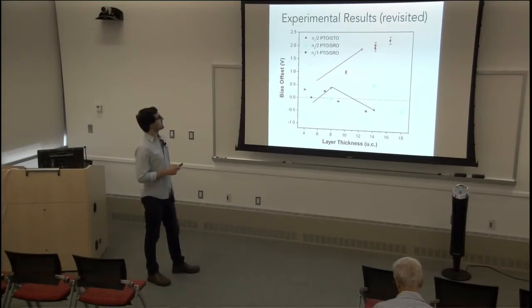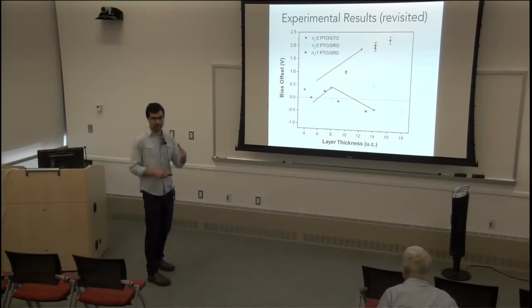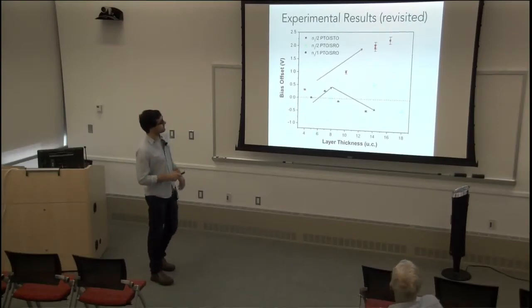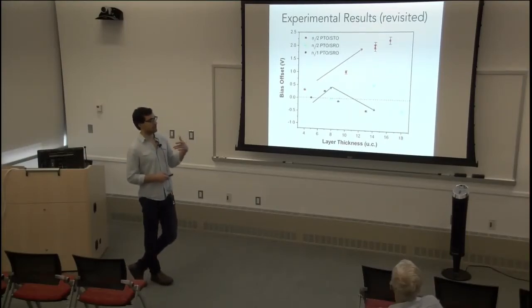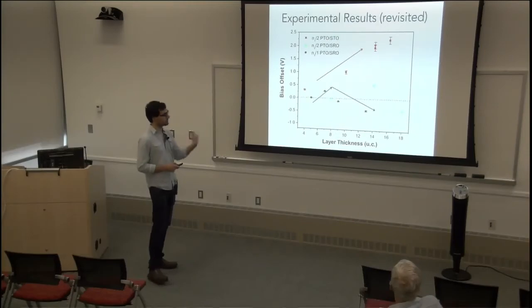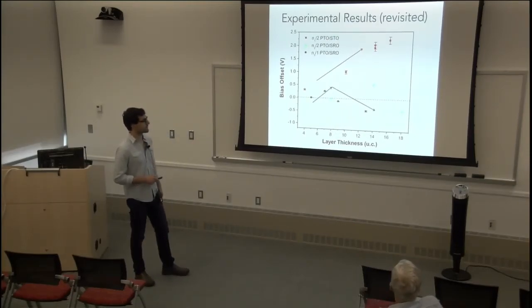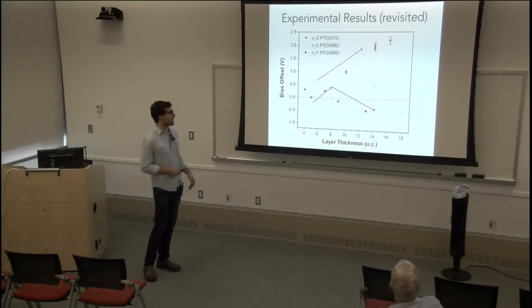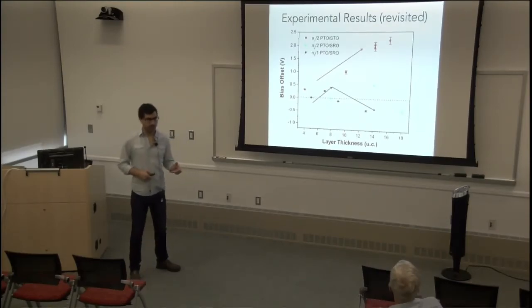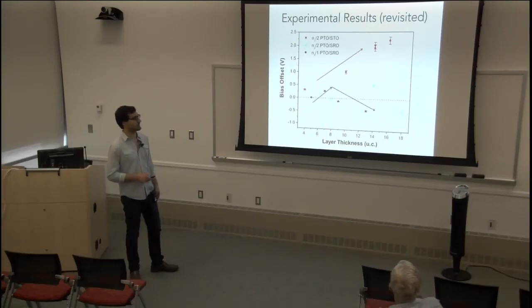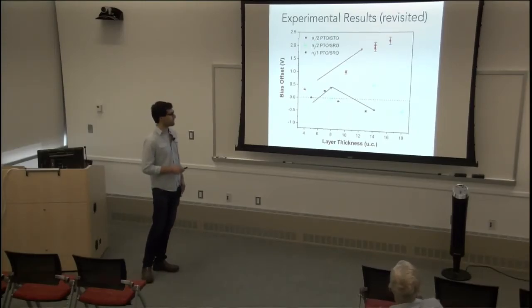Okay, so I talked about lead titanate, strontium titanate, and then lead titanate, strontium ruthenate. The initial bias is coming from the fact that you have an asymmetric interface, and once you increase the lead titanate layer thickness, the strength of the asymmetry decreases significantly, and then what is causing the bias in this region is the fact that you have oxygen vacancies. And the fact that the trend is different is because, if you remember, the oxygen vacancy at the interface has the opposite direction to the direction of the asymmetry. So that's why you have this reversal in the sign of the bias.